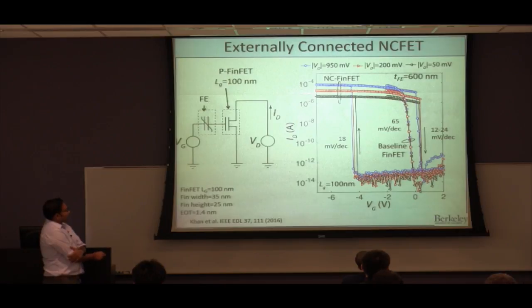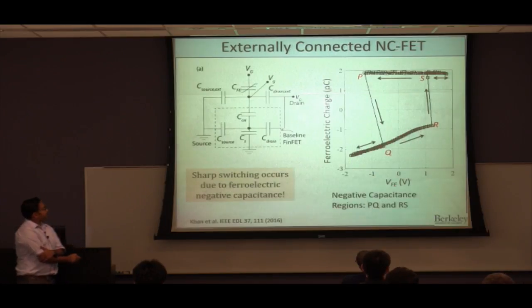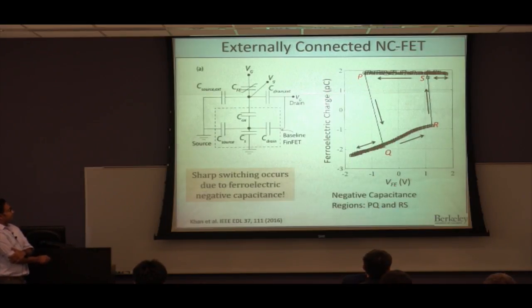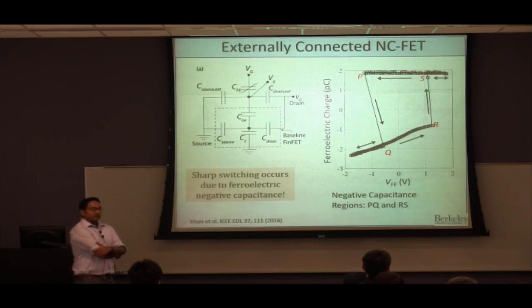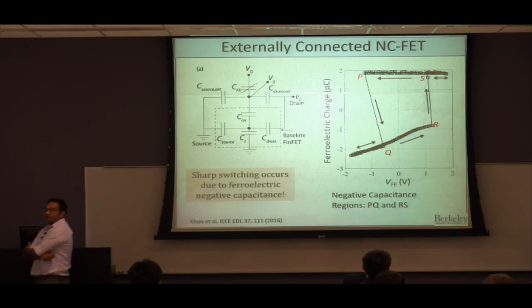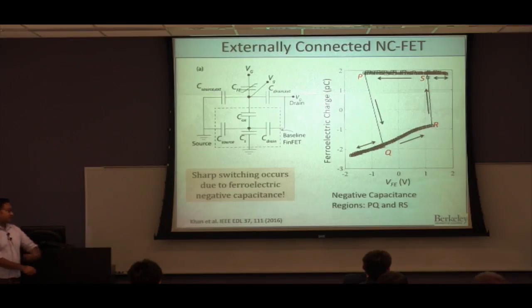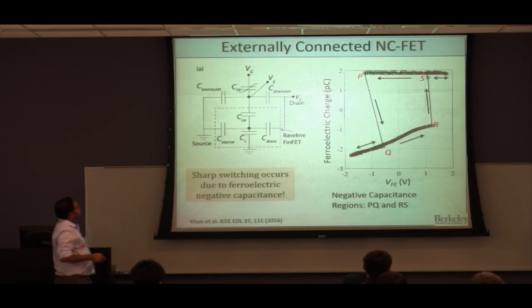Just to make sure that this is coming from the negative capacitance effect, we extracted the charge voltage characteristics of the ferroelectric, and in the charge voltage characteristics, we could see that there is a negative slope here. Which essentially ensures that this effect is happening because of the negative capacitance behavior of the ferroelectric.